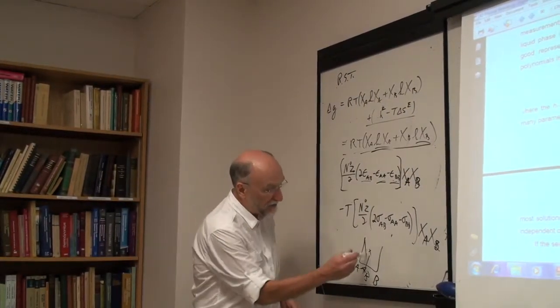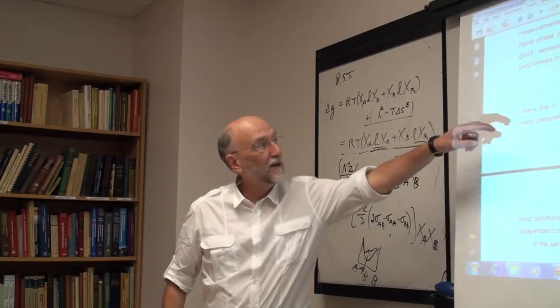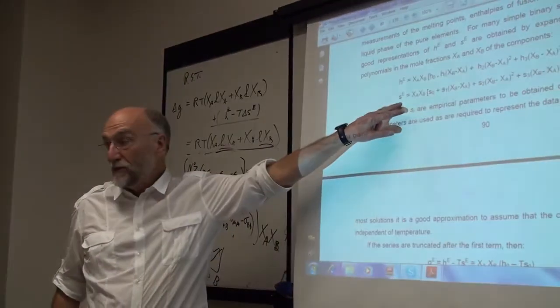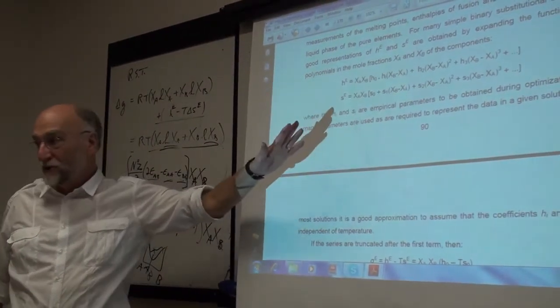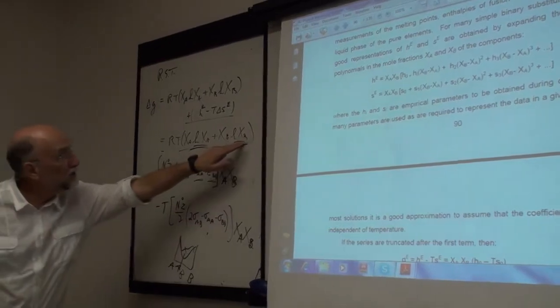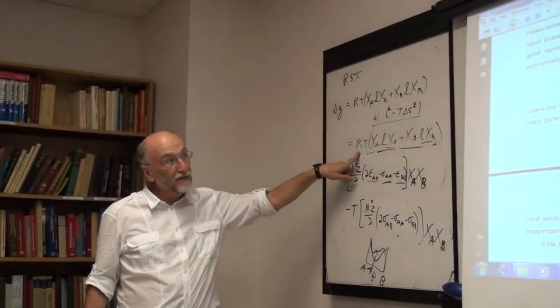You're going to get heats of mixing, and I'll show you later, and excess entropies of mixing, that again you really cannot fit with this type of equation unless you put in a very large number of terms, and then everything's all screwed up. What you have to do is change your excess entropy. Your ideal entropy term has to be changed.